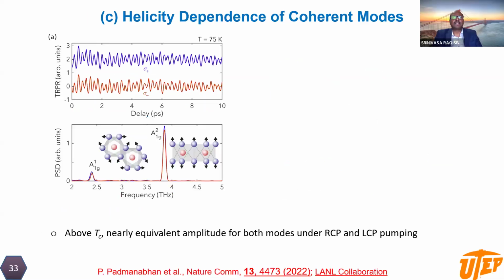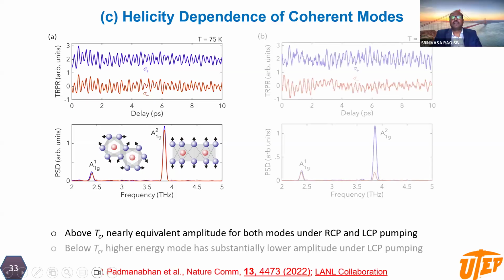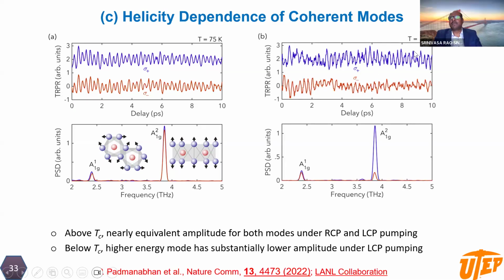And when we did the same experiment by flipping the helicity of this laser pump pulse, and took the spectral density, we see that upon flipping the helicity, the intensity of these two modes remains practically the same, both the A1g mode and the A2g mode. Whenever we conducted these measurements in the ferromagnetic phase and did the same exercise, the A2g mode intensity drastically decreased when we flipped sigma plus into sigma minus, whereas the intensity of the A1g mode practically remains the same. So it means that the A2g mode is a strong function of the magnetic phase of this material.